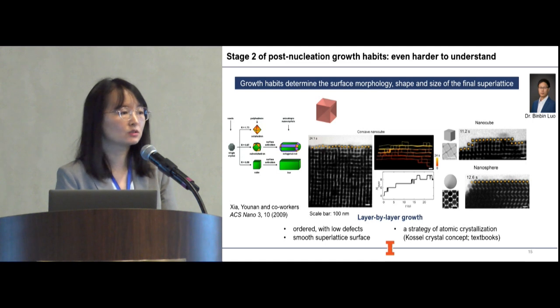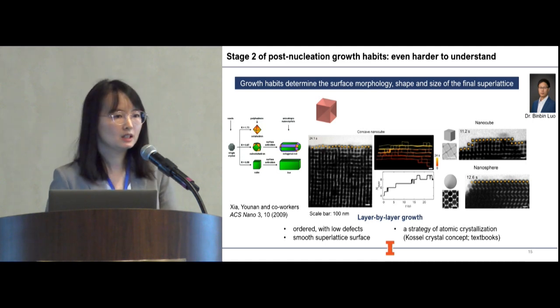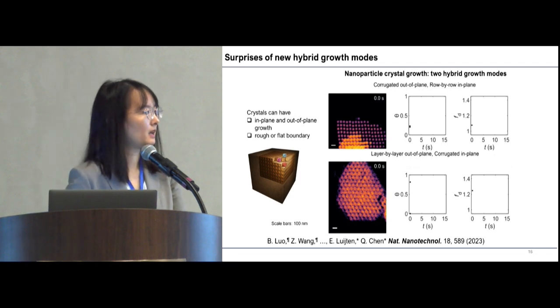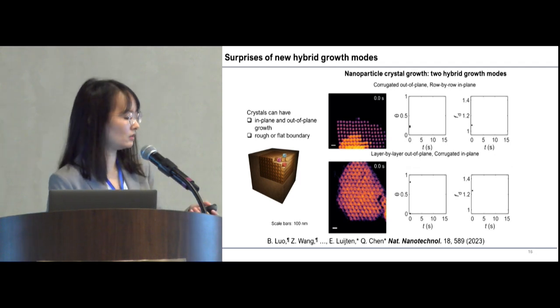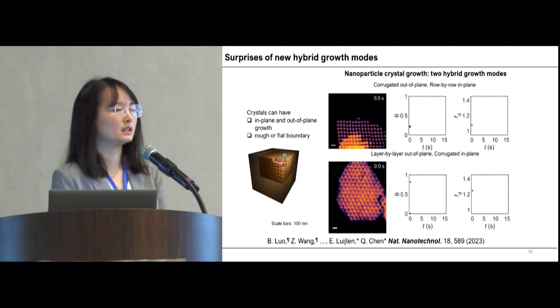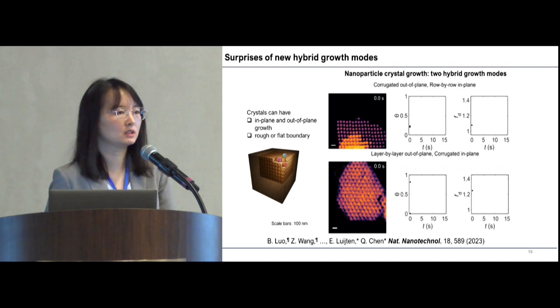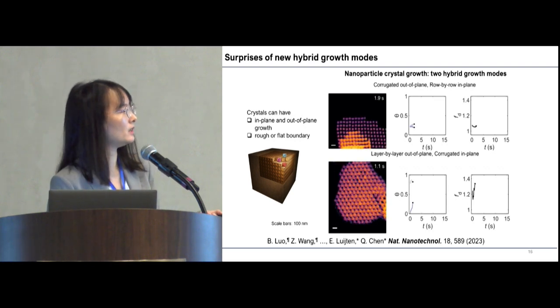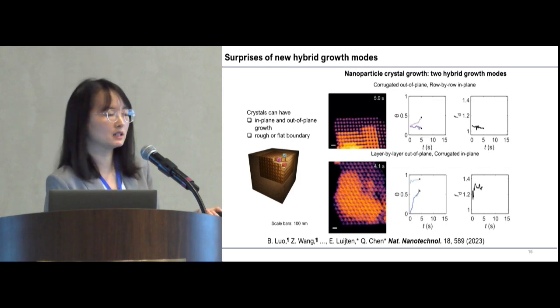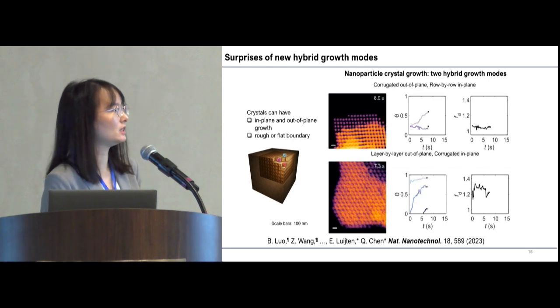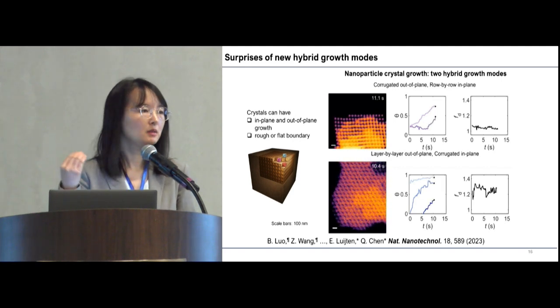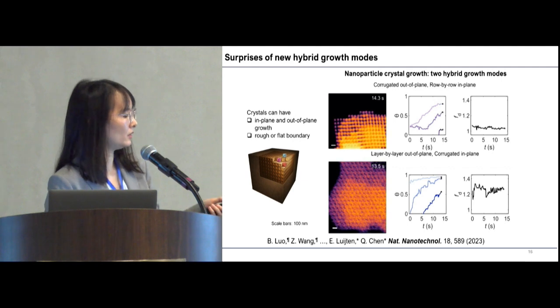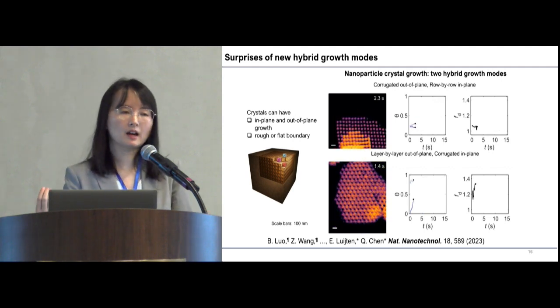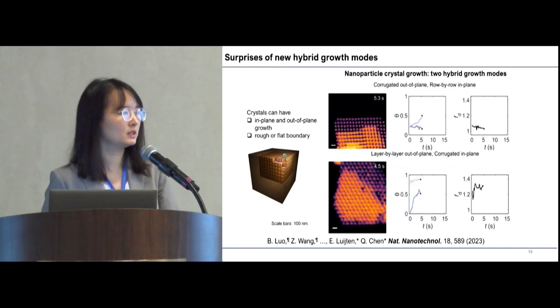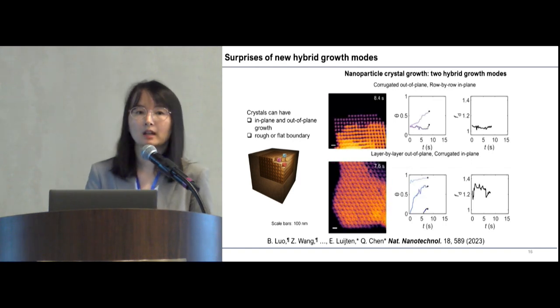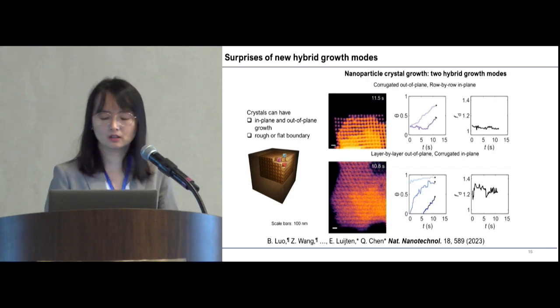But does it mean nanoparticles will always follow this one single growth mode? And that's not really the case. So in our experiment, we're able to actually resolve two different growth directions, the in-plane growth and out-of-plane growth. And we found that we can actually have hybrid growth modes. So in these two liquid phase TEM movies here, the particles of the same color means they're in the same plane. So for the top movie, you're looking at a corrugated out-of-plane growth by very smooth in-plane growth. And then in the movie below, you're looking at layer by layer out-of-plane growth and very corrugated in-plane growth. This is also the first time people are able to experimentally image such hybrid growth modes.